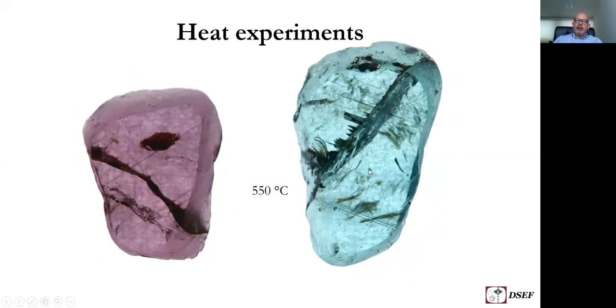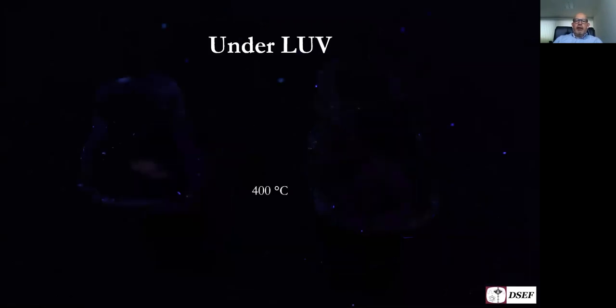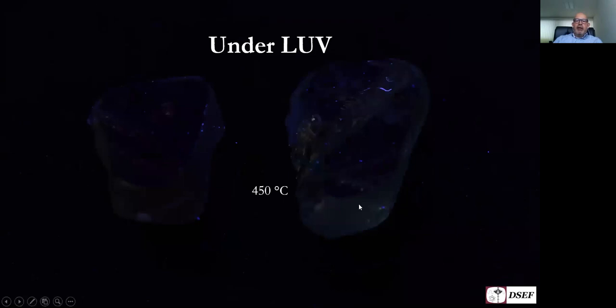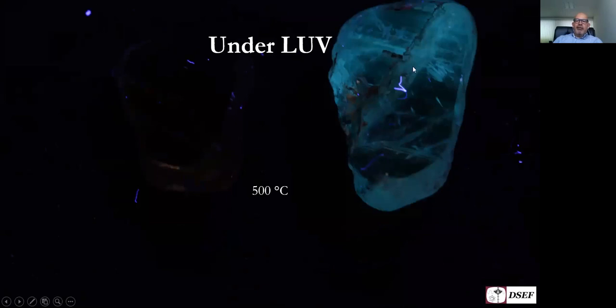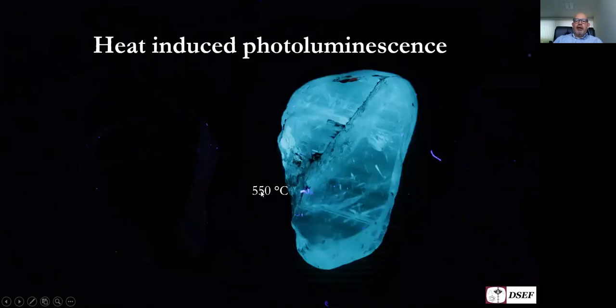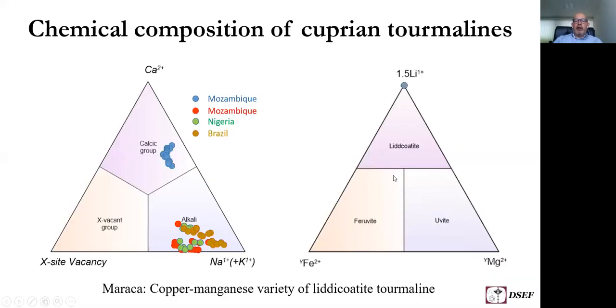And now we look at the same under UV light. 400 degrees, and here you can already see that something is changing. And at 500 degrees, this stone starts to fluoresce in this bluish color. And after 550 degrees, you can see here this luminescence, which is actually induced by heat, and probably also a result of valence change of manganese, but we're still working on that.